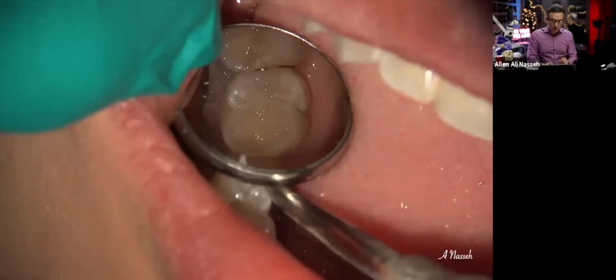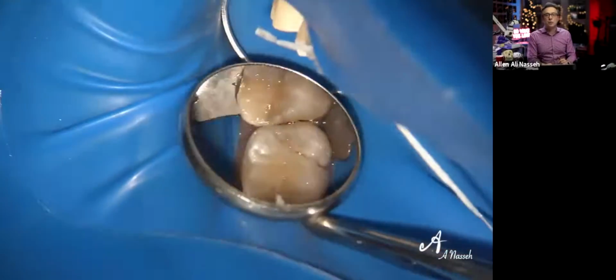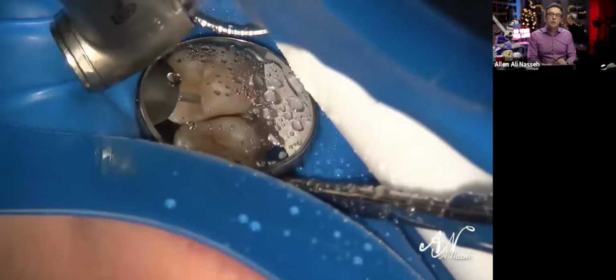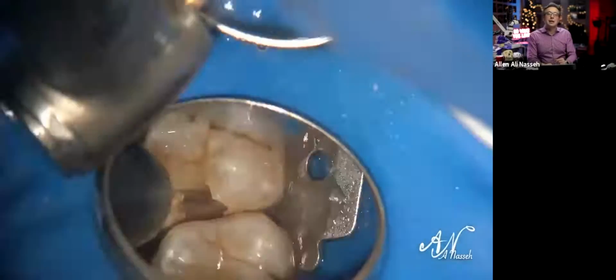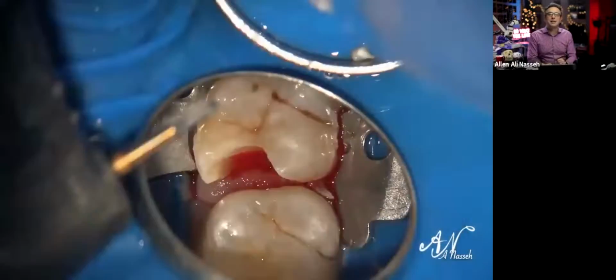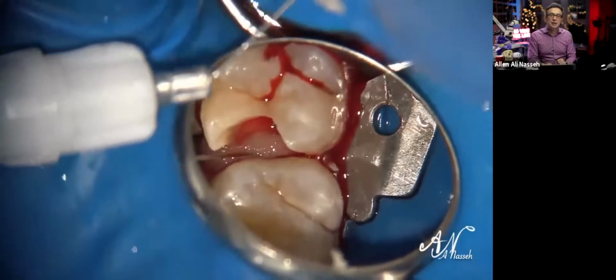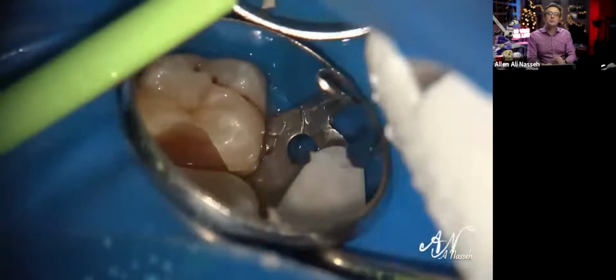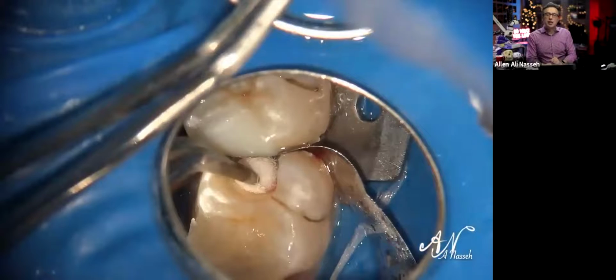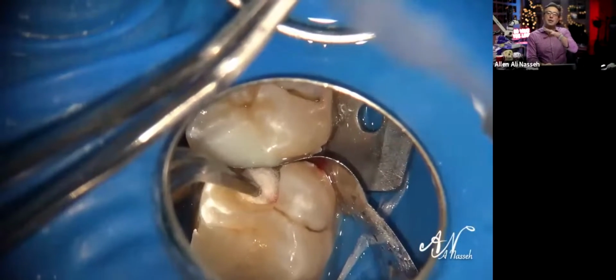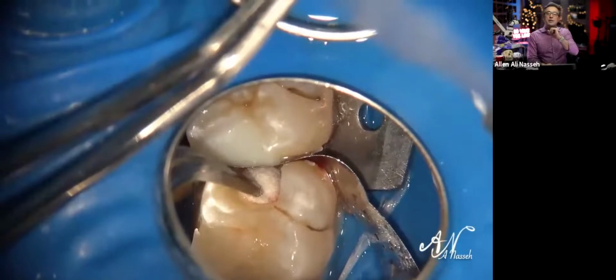And you go in and you start to do your caries removal after proper isolation. We remove the caries, and you have to remove all of the infected and the affected dentin in these kinds of cases. We do get a little exposure, and actually that was just kind of doing a little bit of hemostasis with the col area of the gingiva. But here I'm putting hypochlorite, placing it for 2 minutes or so until I control the bleeding right over the exposed pulp, and then go back.